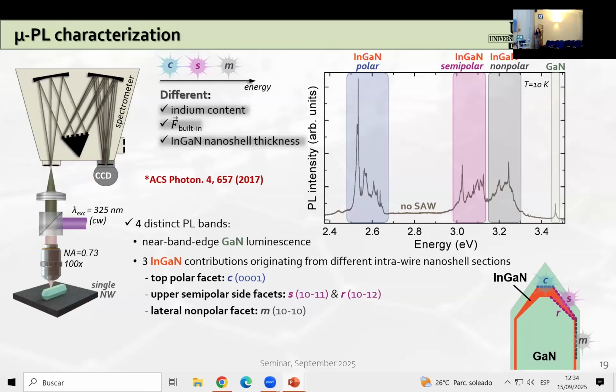What I show here is a typical low temperature micro-photoluminescence spectrum, which is recorded on individual nanowires. This is a confocal, actually homemade, micro-PL system. And as you can see, this spectrum exhibits four different emission bands. The highest energy emission comes from the near band edge luminescence that originates from the gallium nitride nanowire body here. These other three emissions are due to the indium gallium nitride contributions.